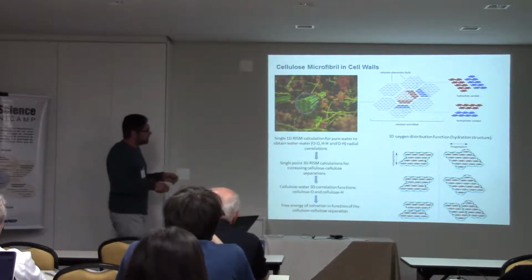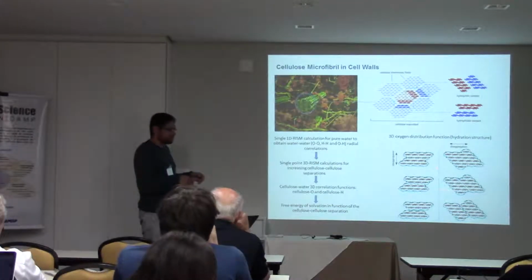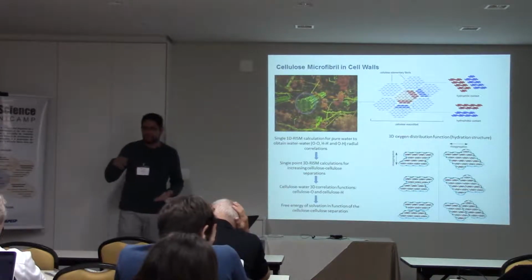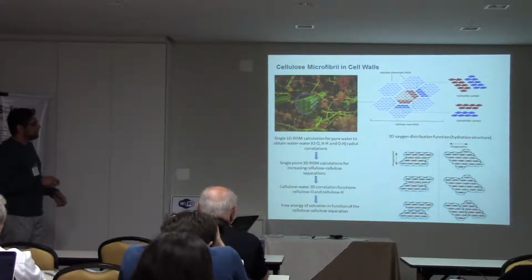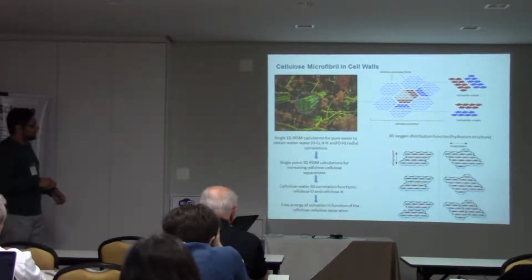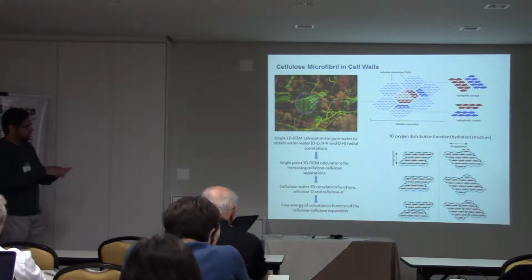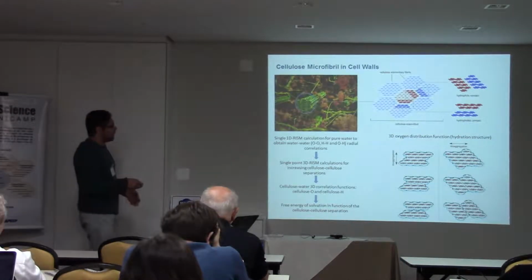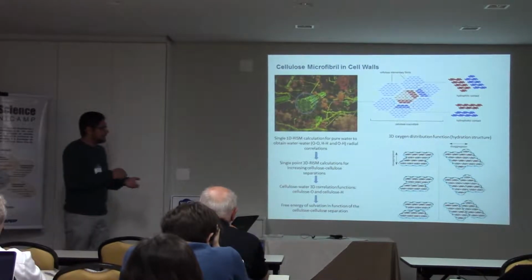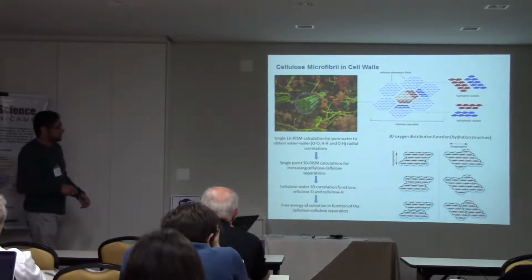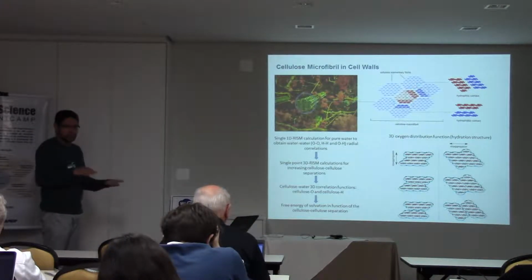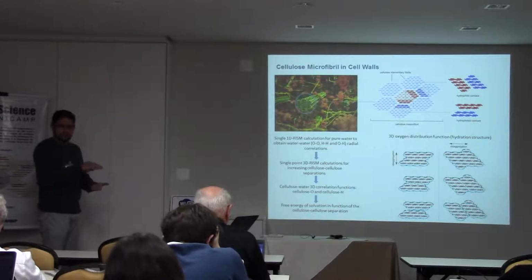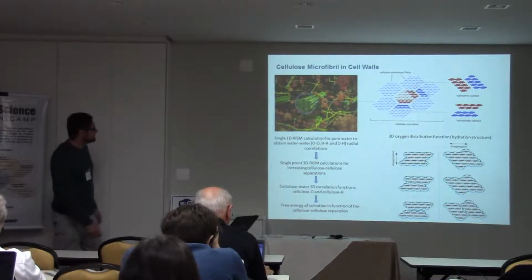So here we have the solvation structure as a function of the separation. You can see here that in this model of cellulose, when they are packed together, the waters are just around, and then as they move apart, water starts to enter in between, and then they create a whole solvation shell when there is no space for water in between the cellulose surfaces.